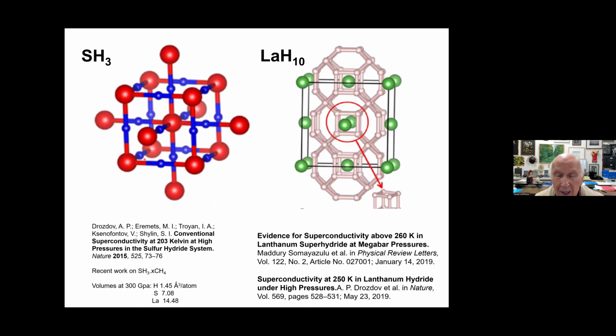But these studies about hydrogen-rich systems have led to some of the most exciting results in recent physics studies. These are the Eremets studies. Eremets just passed away recently, on a mixture of H2S and H2, which can give SH3 material, which is superconducting at 203 Kelvin, as you see. And also Hemley's group and Eremets's group have made a lanthanum H10, which is superconducting at almost room temperature, 260 K.